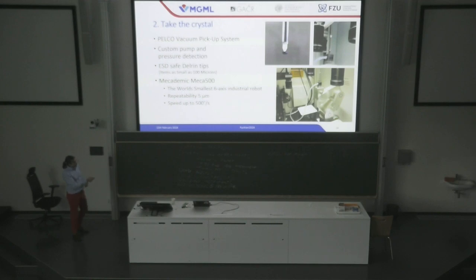We have a very precise robotic arm. It's the smallest industrial robotic arm in the world, and what is very nice is that it's extremely precise. It has a repeatability of 5 micrometers. It has a reach of like 30 centimeters, but if it's in one position, I do some complex movement, I can then go back and I will be in the original position plus minus 5 micrometers, which is ideal for our use case.